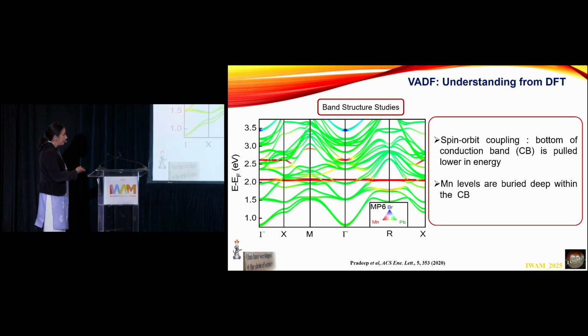band here. But in these nanocrystals, cesium lead bromide, the conduction band, because of the spin orbit coupling, is pulled down much lower, which means the manganese emission is actually buried deep into the nanocrystals. And because it's buried deep, it has chances of interacting through vibrational states. And does it actually interact?